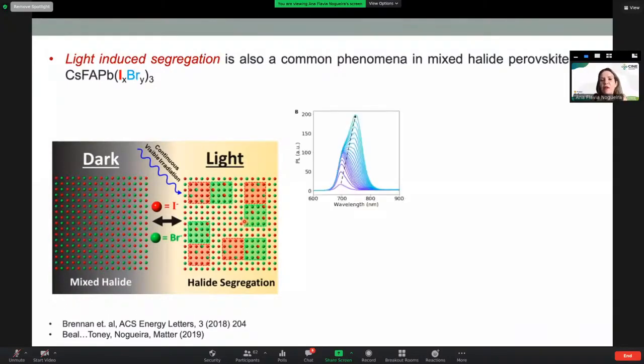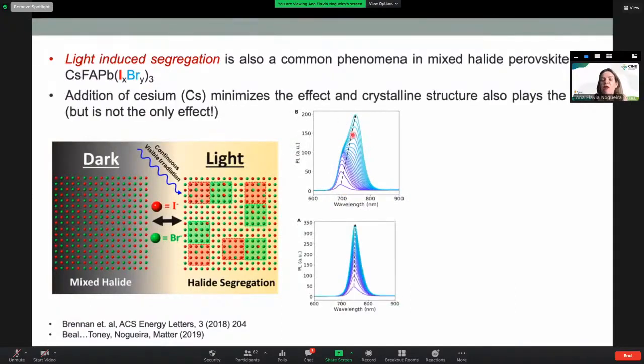When we continue to irradiate the samples, they go through what we call halide segregation. It means that we form regions rich in iodide and other regions rich in bromide. This is very easy to follow by PL. You can see here that after shining light on the sample, you see the evolution of the iodine-rich phase. This can also be stabilized when you have cesium. When you have cesium, you minimize this kind of light-induced segregation.